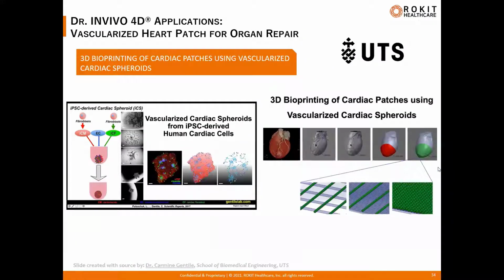In this case, they used the bioprinter, and they used iPSC-derived cardiac spheroids composed of fibroblasts and endothelial cells. They combined them into multi-cell type spheroids, which are then mixed with alginate inks to form a bioink. The ink is then printed onto a hydrogel patch to create a model for the vascularized heart patch.